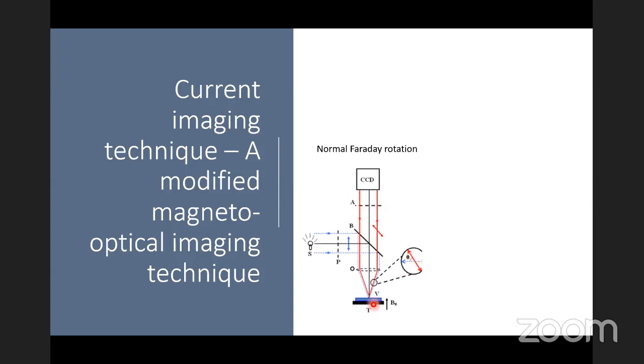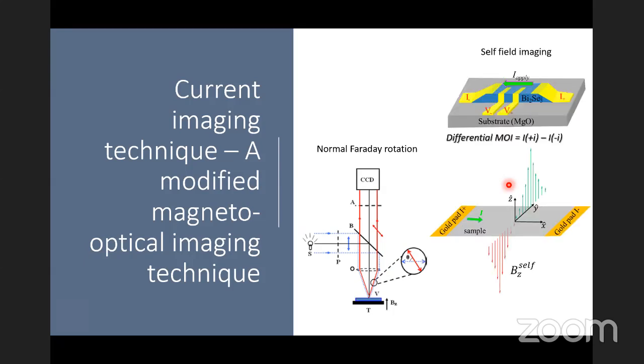Now this angle depends on the local field. Typically these could be magnetized structures on the sample, but instead of a magnetized structure, suppose the local field is generated by the current itself. Namely, you send a current and you generate a magnetic field; can you see that magnetic field using our technique? And we actually can see it. So we make samples with planar contacts, and then we send in a current, and we do something called differential imaging. I'll not get into the details, but when you send the current through the sample, there is a magnetic field distributed across the sample, generated by the current, namely the self field of the current. And then using this technique, we image the distribution of the current on the sample surface.